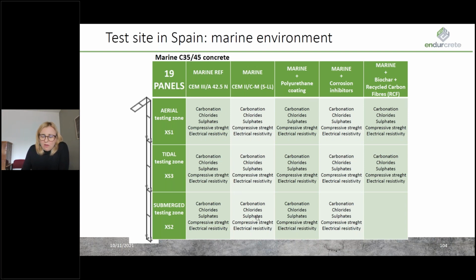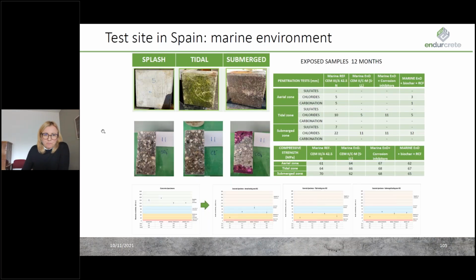You can see all the tests which were performed on those samples exposed to those environments, which included durability tests, carbonation, chloride, sulfates determination, and then compressive strength and monitoring with electrical resistivity sensors. On this slide, we can see the different samples from different zones, which is quite significantly different. So in the splash zone, we have a clean concrete surface. In the tidal, we have some algae formation, and in the submerged, we have some biological growth. Overall, the samples were performing very well.